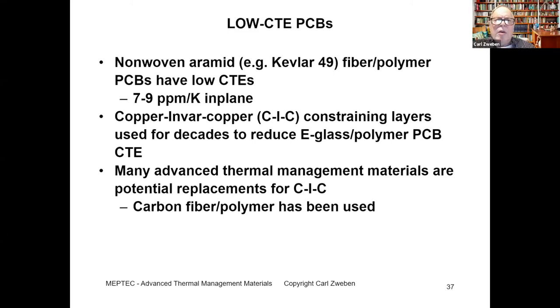We talked about the fact that e-glass polymer printed circuit boards have high CTEs. And at least at General Electric and in some parts of the industry, we were able to reduce the coefficient of expansion of the printed circuit board using copper Invar copper constraining layers. But we now have printed circuit boards where instead of glass fibers, we're using aramids, and they have low in-plane CTEs in the range of 7 to 9 parts per million per degree Kelvin. And I'll show you an application later on.